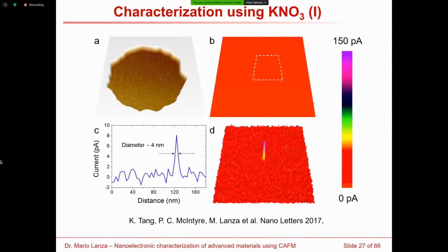So in the next experiment, together with my student, we did one experiment that was really, really difficult because we needed to find one conductive filament that is around 4 nanometers in one window whose diameter was around 40 micrometers. So this was a very challenging experiment. We needed to increase the resolution of the map a lot, which decreased the speed of the scan. And this scan that you see here took us nearly 2 hours.